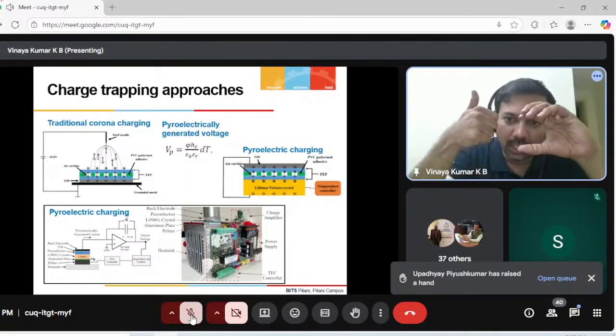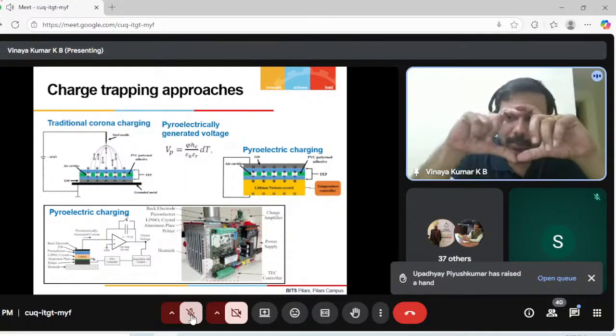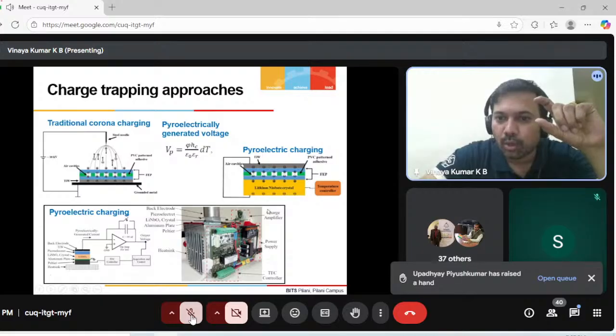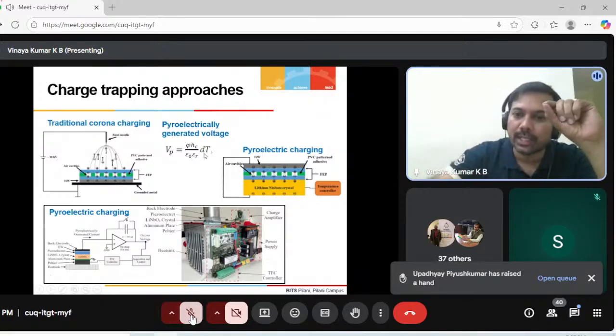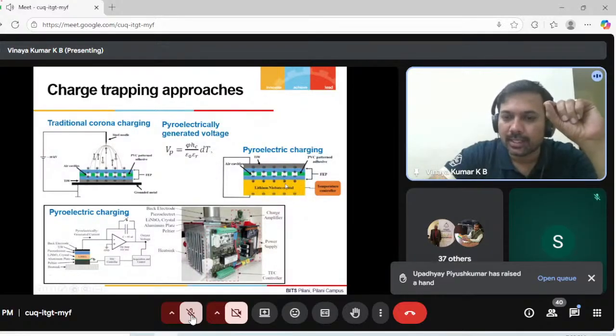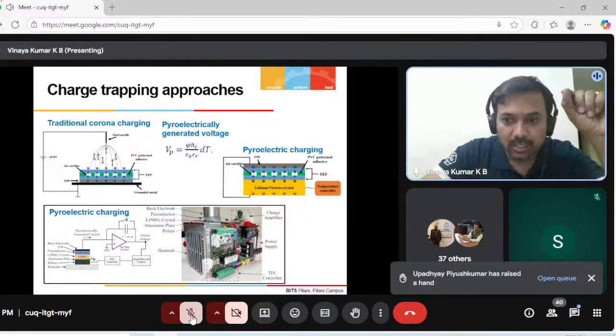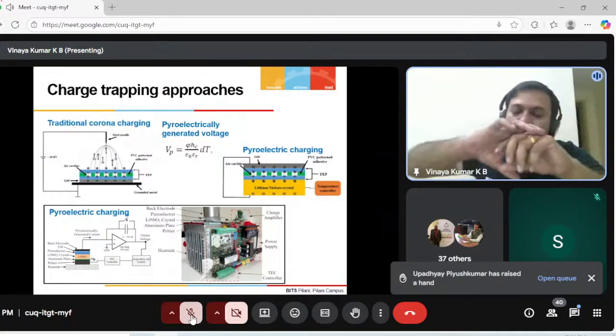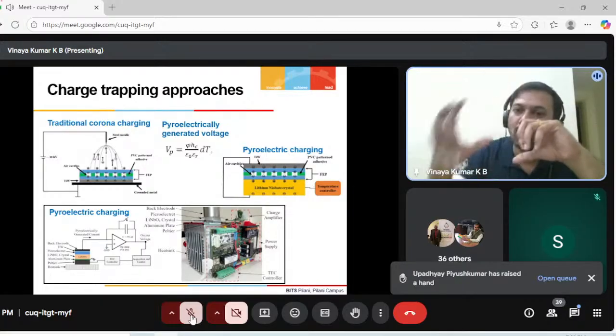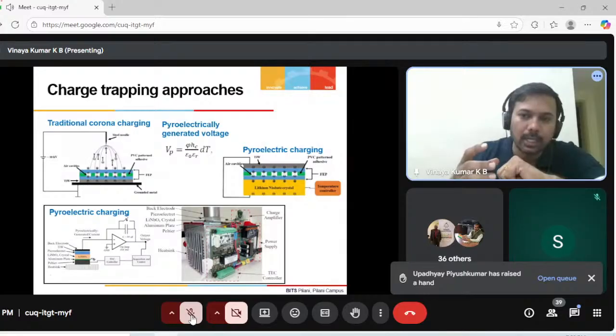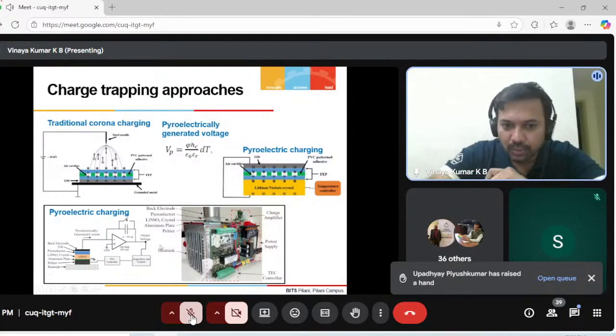This means we create a dipole in these voids by applying just a very small temperature change. The temperature we applied is only 3 to 4 degrees, but the surface potential generated is in the range of tens of kilovolts, a very high surface potential. We even use this to break down air molecules around it, for example as an ionization source for a mass spectrometer. We built this full instrumentation. As you can see here, it's a pyroelectric charging system to trap the charges on this ferroelectric material.